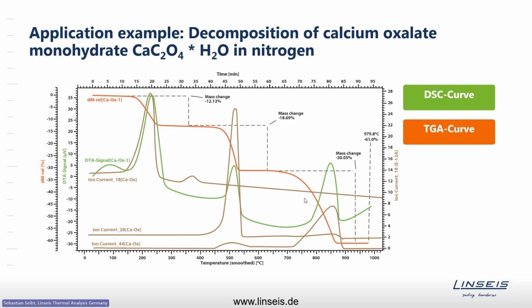And out of this, so coupling a mass spec, you can get pretty good information on what exactly is happening. And as said, the decomposition of calcium oxalate is well known, and we use it as a kind of reference material to check if the TG and DSC lines and curves fit the literature values, and if everything is fine with the instrument.